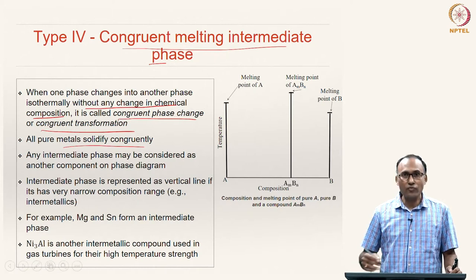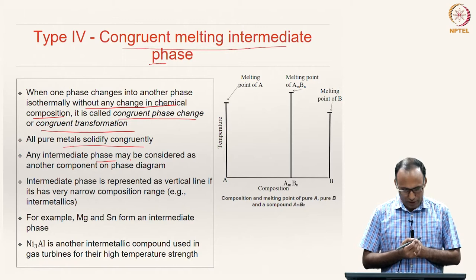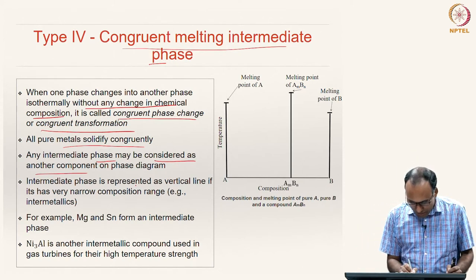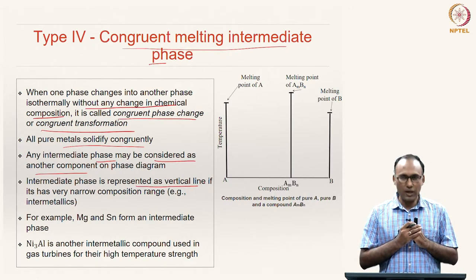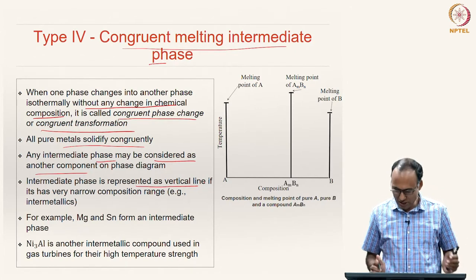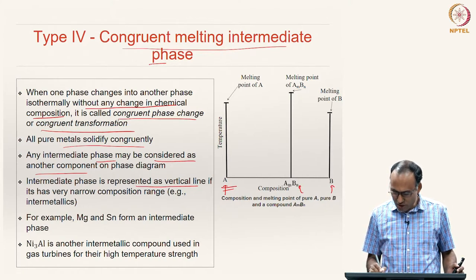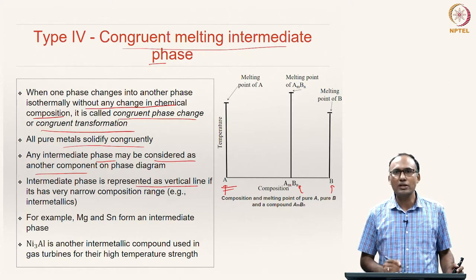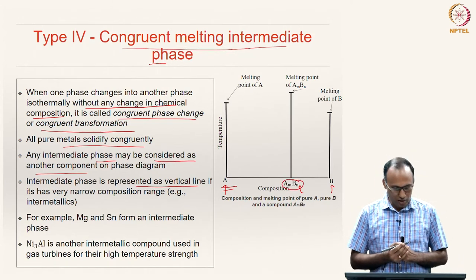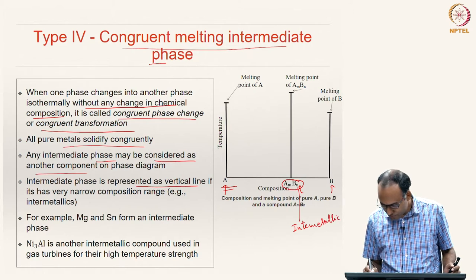If in an alloy system there is an intermediate phase that is solidifying congruently, it may be considered as another component on the phase diagram. The intermediate phase is usually represented as a vertical line if such solidification happens over a very narrow composition range or only for a particular composition. For instance, in the right-hand side diagram, you have pure metal A and pure metal B, and for a specific composition A_M B_N the melting happens at constant temperature. This particular compound is called an intermediate compound or an intermetallic compound, because it is between two metals.